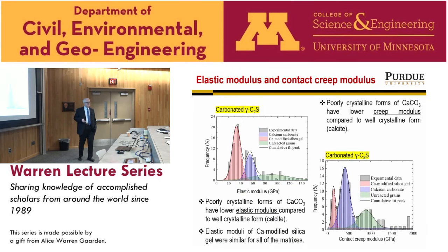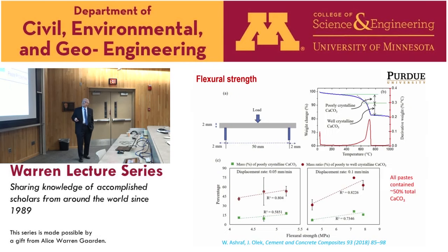And the summary of that work is actually presented here. What we found out that poorly crystalline forms of calcium carbonate have lower elastic modulus compared to well-crystalline forms like calcite. Elastic moduli of calcium-modified silica gel were similar for all matrices. And this is creep modulus, and again, poorly crystalline forms of calcium carbonate had lower creep modulus compared to the well-crystalline forms. So that tells you that if you want to maximize the mechanical performance, you need to do something to either produce more of crystalline forms, or if you are maybe interested in material that is a little bit more ductile, maybe you need to produce less of those crystalline forms.